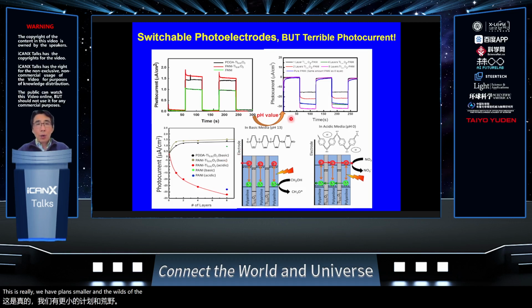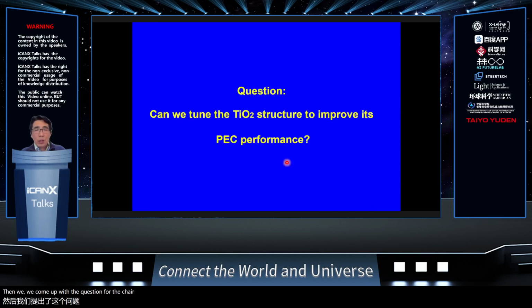One of the key problems we found is that the nanosheet itself is very thin. When we prepare the multilayer thin film, the nanosheets cover the substrate layer by layer, and when the electron passes through, it needs to go from one layer to another. That's the transport, and the transport pathway is not that smooth. There are a lot of defects and trap sites. Another thing is that being very thin, it may not absorb the light very significantly. Then we came up with the question for TiO2: how can we design the structure to improve the efficiency, that means to unlock the full capacity of this material?